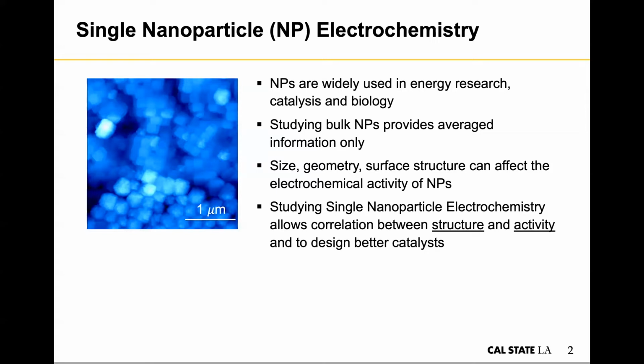But on the other hand, I'm showing you an AFM image of a batch of Prussian blue nanoparticles that was synthesized. So it's very obvious that with the same batch of particles, you can see different sizes, different surface structures, and we believe that the size, geometry, and surface structure can all affect the actual electrochemical activities of nanoparticles. And if you use a method that can only give you average information, you cannot establish a correlation between the specific structure of the nanoparticle and the induced electrochemical properties or catalytic properties.